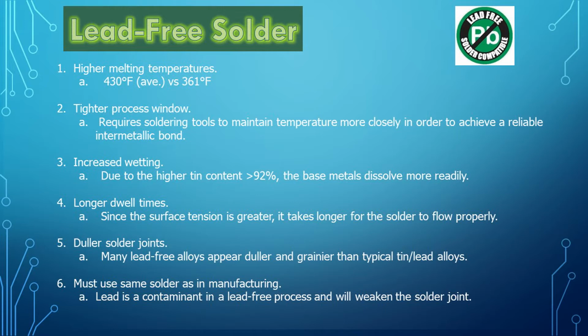Something else that I need to mention here that's very important: do not mix different solder alloys on the same project, as unpredictable results may occur. For example, if you mix a tin lead alloy with a lead-free alloy, the melting temperature will change and the solder joint will be severely weakened.